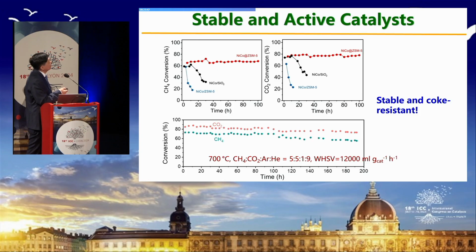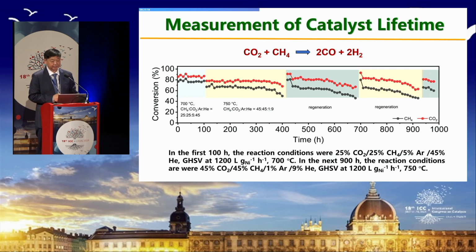Similarly, you can see the methane conversion and CO2 conversion are all very stable with the nanoparticles fixed with zeolite. Here I show you the lifetime: even at 200 hours there is just a little reduction in activity and selectivity. So after fixing the active site with zeolite crystal, it is stable and coke resistant.